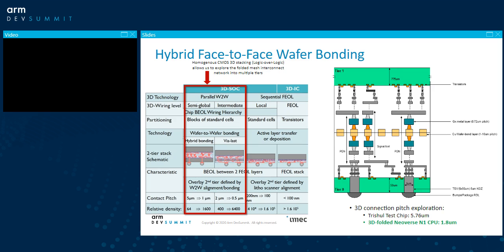Essentially, this kind of wafer-to-wafer bond package is around 5 micron, so the alignment must be a fraction of this pitch. The liquid is dropped at the center of the wafer and sprayed for chemical bonding to stick the wafers. The wafer structure is then put in an oven to heat, at which point the metallic bonding occurs and the copper bonds truly and physically attach to each other.